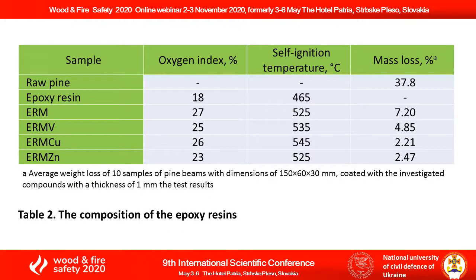To determine the flammability of the research samples, the oxygen index or OI method was used. In the study, on a series of 5 samples, the minimum oxygen concentration of the oxygen-nitrogen mixture necessary to maintain stable combustion of these samples was determined.